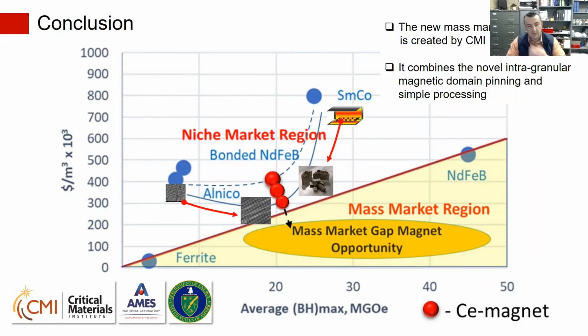We can look at this system from two perspectives. We can look at this system from a samarium cobalt perspective and from an ALNICO perspective. Samarium cobalt is using expensive processing and has more than 55% of cobalt. If we imagine that our magnet is basically a samarium cobalt derivative, then we reduce already cobalt to ALNICO levels, if you want, and we are basically producing it differently. So we are casting. So we are reducing the price of samarium cobalt.